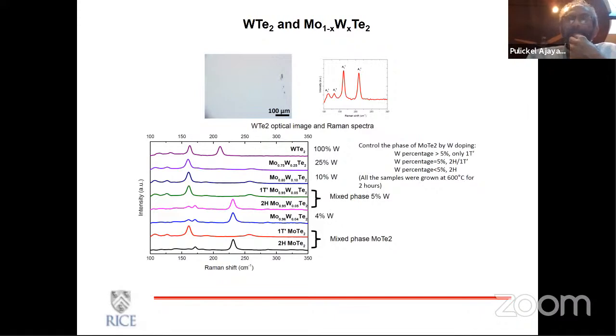that if I take telluride and start to dope them with another metal, like, if I take molybdenum telluride and start to make doping with tungsten, then it goes towards the more metallic phase. So tungsten telluride is actually metallic. It doesn't really easily form a semiconducting phase. And molybdenum telluride doped with tungsten actually gets more metallic nature.